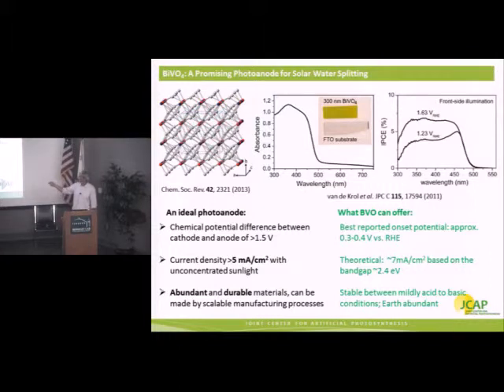Shown here, we have an absorption spectrum of the material. There's an absorption onset right about 500 nanometers. This is where it starts capturing the solar spectrum. So it's not perfect. We lose everything below, so wavelengths longer than 500 nanometers. But for an oxide photoanode, this is pretty good. On the top right is shown the IPCE, which is effectively the external quantum efficiency of the device. We have a similar onset. Maybe it's slightly shorter wavelengths. But again, we're capturing quite a bit of the solar spectrum of this material.